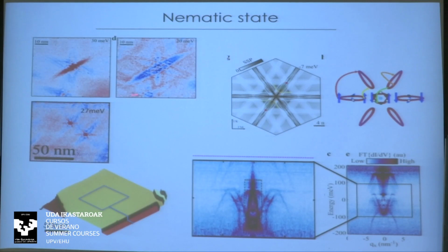First of all, the quasi-particle interference patterns are very anisotropic. So generally, you would expect to see all 3 ellipses to look the same and have the same sizes. We can actually extract the sizes of these ellipses, and we see that in one direction, the ellipse is much longer than the other two.